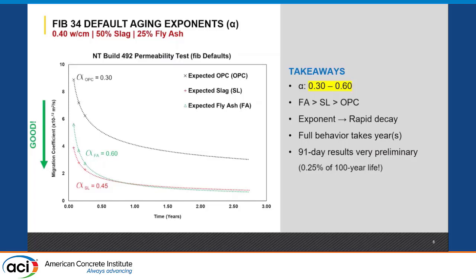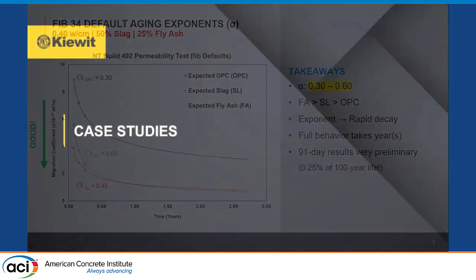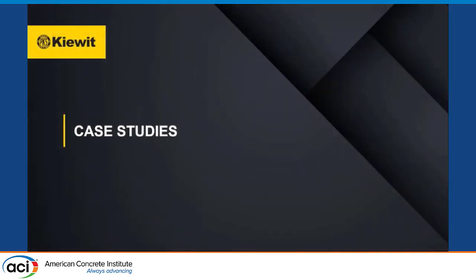We see that fly ash is more effective than slag, which is more effective than OPC. It's an exponent. There's a rapid decay. Takes years, but we really pretend that we know what we're talking about at 90 days, which is 0.25% of 100 years. So that was a little bit of background on permeability. Hopefully you guys are the experts by now after that.